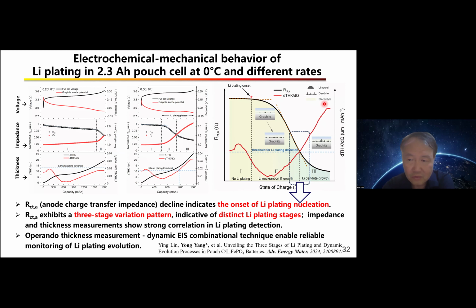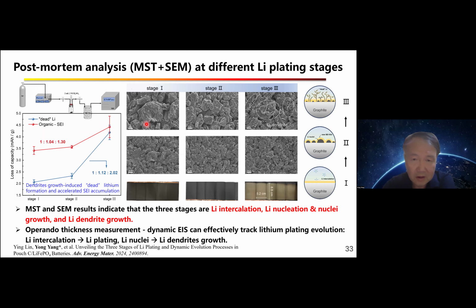Because we want to make sure our explanation is reasonable, we also used MST techniques to measure the dead lithium formed on the graphite electrode. We also used SEM for stage 1 or stage 2, where lithium dendrite formation cannot even be seen, but after stage 3, you could see some of these lithium dendrites.